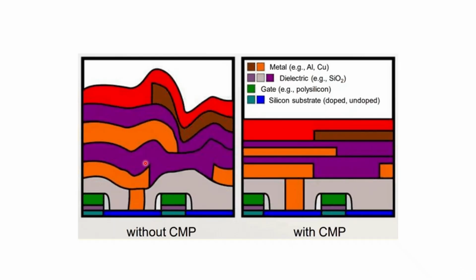Now, when you don't use any CMP process, then when you deposit different layers, they follow the topology of the previous layer, and you end up having something like this. But if you can afford to do CMP polishing at every stage, then you can form much more well-defined structures. This may not seem that important, but on a planar surface on top, you can use high-resolution lithography, whereas here you cannot because of the focal depth changes.